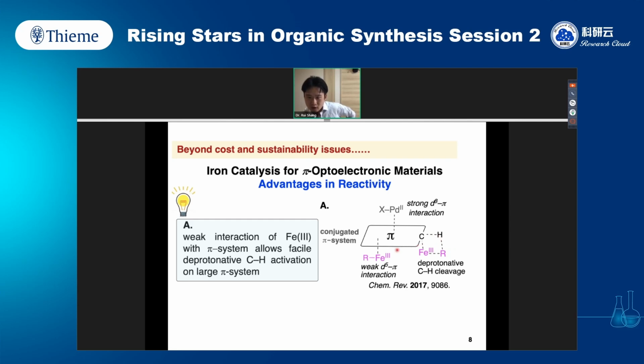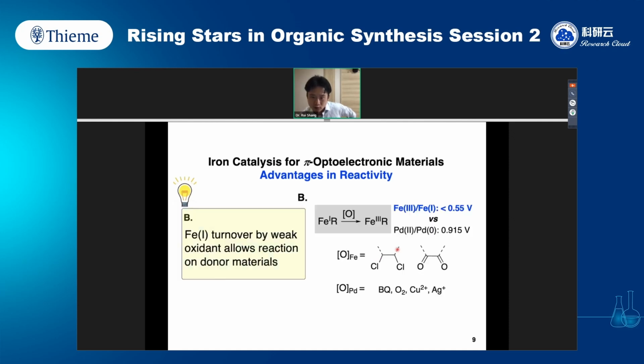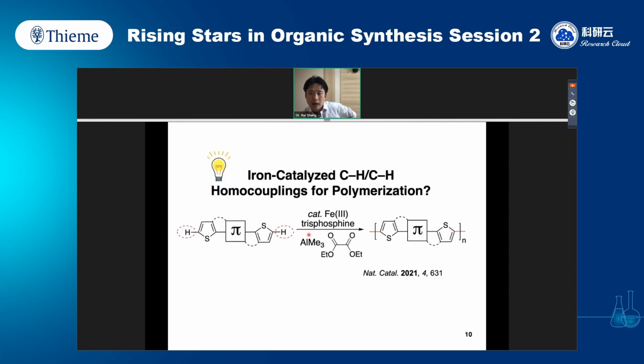If we consider large pi conjugated systems, one such choice is, of course, conjugated polymer synthesis. The second is that iron turnover needs a very weak oxidant, such as dichloroalkene and 1,2-dicarbonyl compounds. This comes from the inherent low redox potential of iron-1, iron-3. This is a critical point for working on pi-extended molecules, which have high HOMO levels. It means the molecules, especially donor molecules, are easier to oxidize. So our first target is how we can apply the iron-catalyzed CH-CH homocoupling to CH-CH polycondensation reaction.